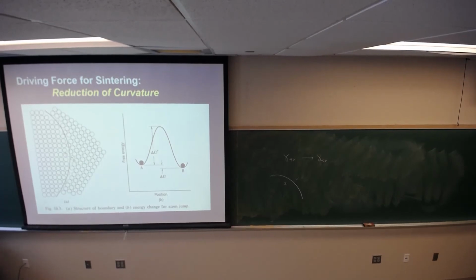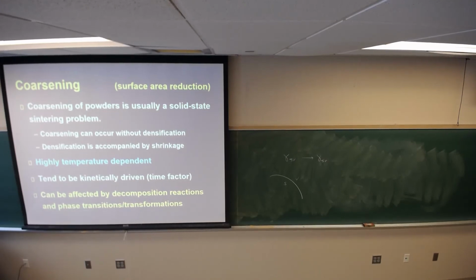So we differentiate sintering into sintering and densification. What's the difference? Any process which changes the morphology of the grain or changes the grain boundary is sintering. Processes that reduce porosity are densification. So we differentiate that way. Coarsening is usually a solid state sintering problem. Okay, coarsening could occur without densification, and what we found, a fascinating result recently, is that the surface area reduction associated with sintering appears to be independent of the densification process. So if I create bodies that are flocculated or dispersed, I get different densities in those bodies at a different temperature, but my measured surface areas are essentially indistinguishable.